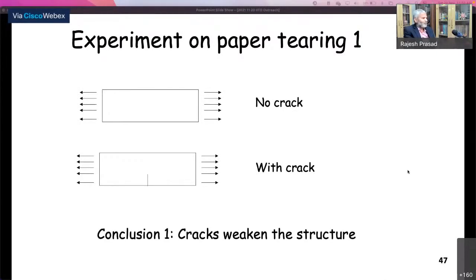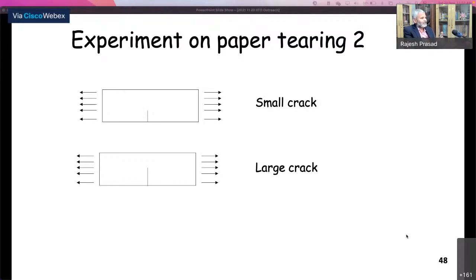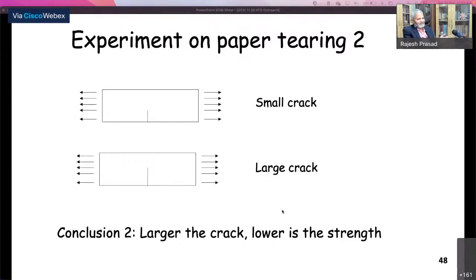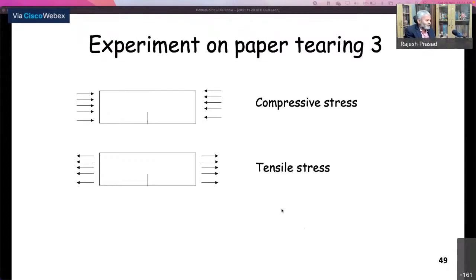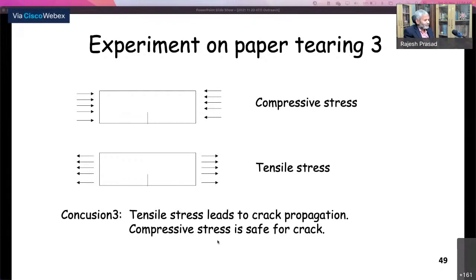So let us conclude. Our first conclusion was comparing two sheets, one with a crack and one without, and we decided cracks weaken the structure. You know that from your childhood. The second was with a smaller crack and a larger crack, and we again decided that larger cracks lower the strength. This also you know from your childhood, because we have experienced crack propagation and fracture in our life. The final one, which was the interesting one, was that compressive stress is safe for a crack, and this is actually used.